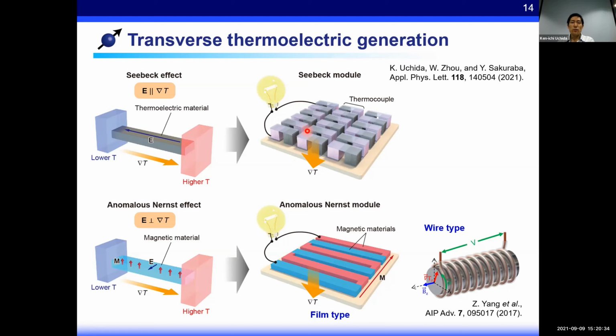On the other hand, in the anomalous Nernst effect, heat and charge current flow perpendicular to each other. So a simple sheet structure works as a thermoelectric device, and its output power is proportional to the device area, and output voltage is proportional to the length along the electric field. So even when making a thermopile element to enhance the voltage, as shown here, a simple in-plane zigzag structure is sufficient. A thermopower can also be obtained by winding a wire around the pipe-shaped heat source and directing the magnetization along the axial direction.